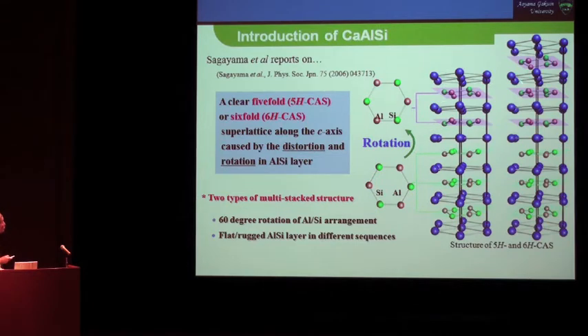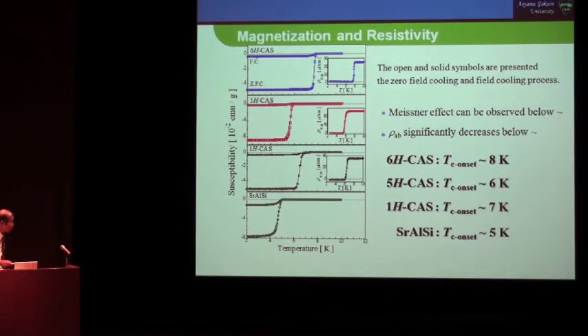However, the next step is to grow a single crystal. So Koreakun started to grow a single crystal. After growing a large single crystal, we noticed that TC is different for the same calcium aluminium silicon material.